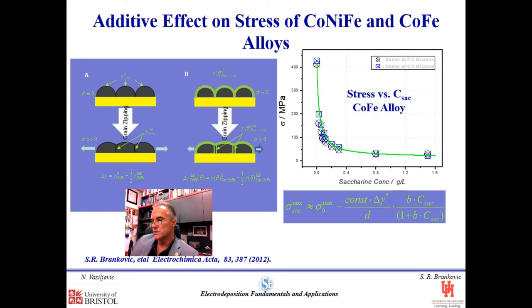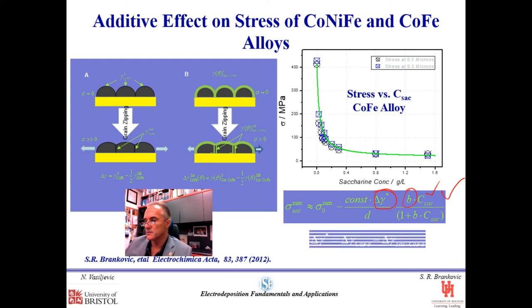So the effect of additives, and the model that explains the effect of the concentration of additives in the solution on the resulting stress in the deposit, or the maximum stress in the deposit, is shown in this relation here, where saccharin or additive concentration is shown here. This is the equilibrium adsorption constant of the additive, and this term here is a specific term that I'm going to explain in a moment, and this is the maximum stress that we have without additives if we do electrodeposition. What is the stress in the deposit without the presence of the additives in the solution?